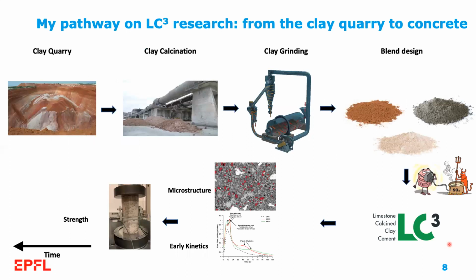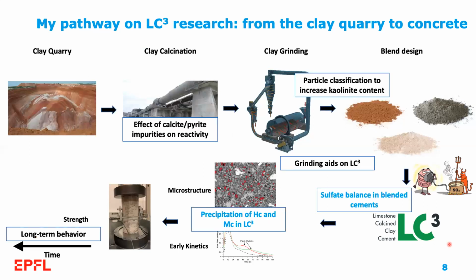During my doctoral process, I explored different aspects of the LC3 technology, from the clay quarry to production of the blend and characterization of its properties at early and long-term ages. In particular, I conducted studies on the effect of calcite and pyrite impurities on the reactivity of the calcined clay, the use of particle classification techniques during grinding to increase the kaolinite content of low-grade clays, the application of grinding